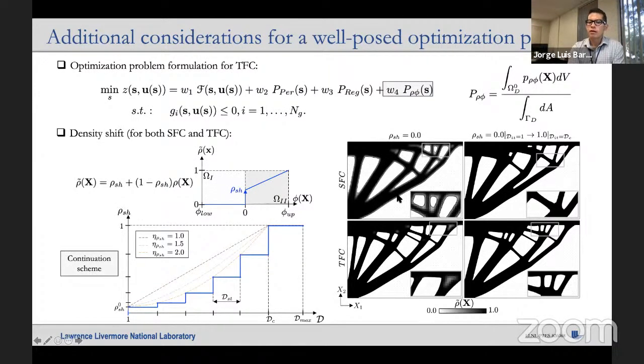So for the single field coupling, by construction, if you remember the previous expression, they're linearly dependent. So in the vicinity of the interface, you have intermediate densities without the shift. And if you include the shift that goes to one at the end of the optimization problem, this is removed. Something similar happens to a two-field coupling, but here, since they are completely independent, your intermediate densities can be anywhere, and in this case, they're just somewhere in the material side, and they're also removed by the shift.